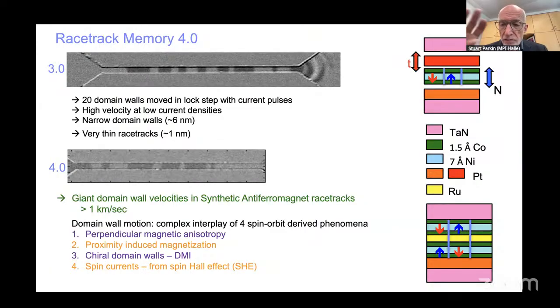So the racetracks here are very, very thin. And down below, you can see this synthetic anti-ferromagnetic racetrack. You can see a series of domain walls moving backwards and forwards by current pulses that are applied in the positive and then the opposite direction. And these domain walls move at speeds of more than 1 kilometer per second. And in the bottom right, you can see a cartoon of the structure.